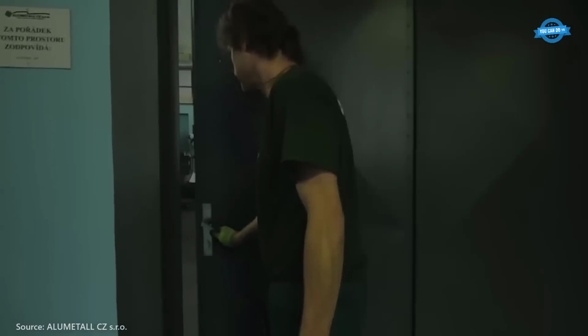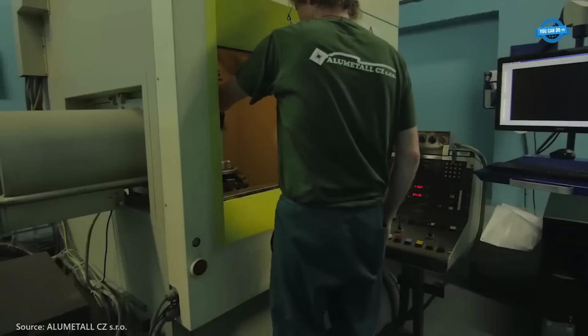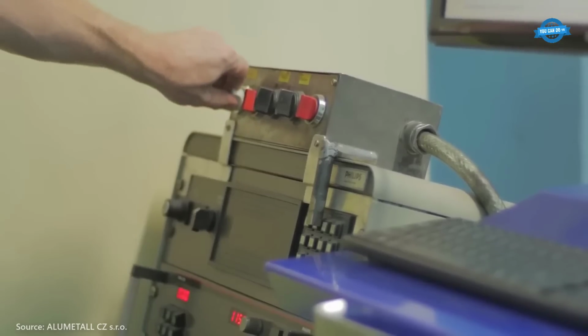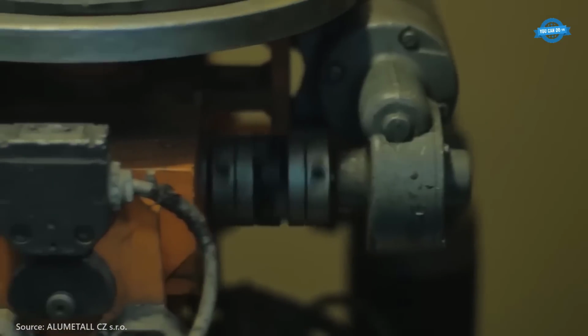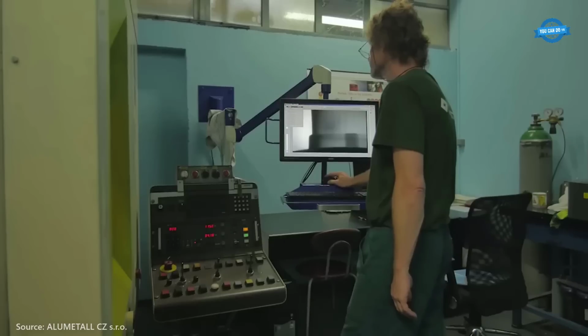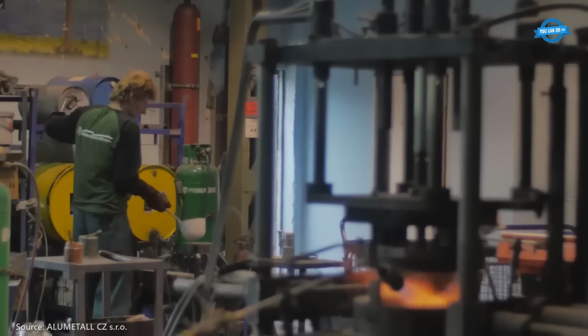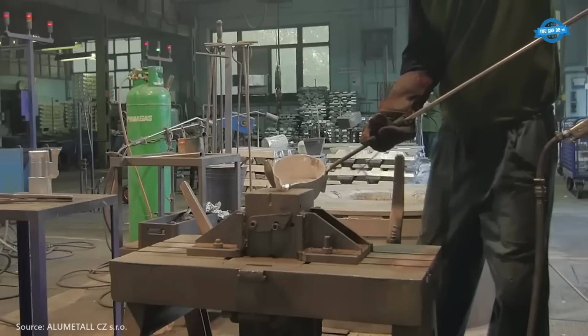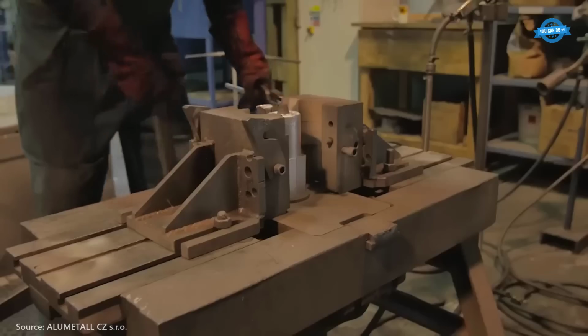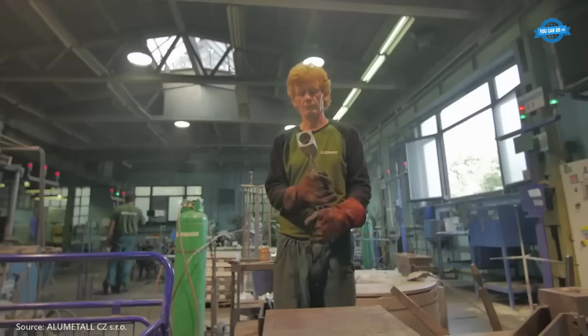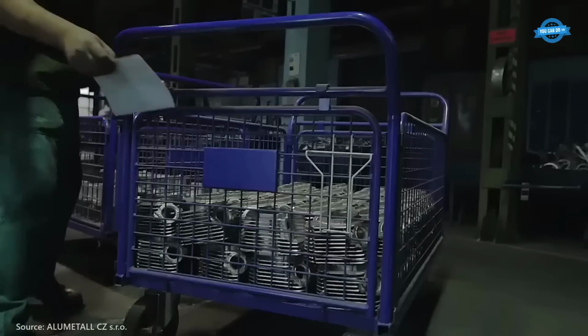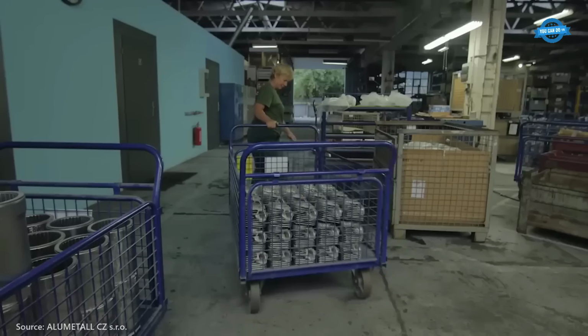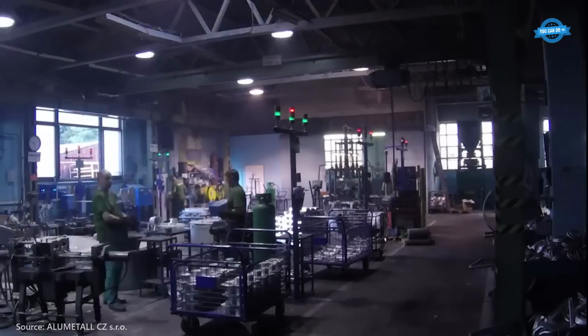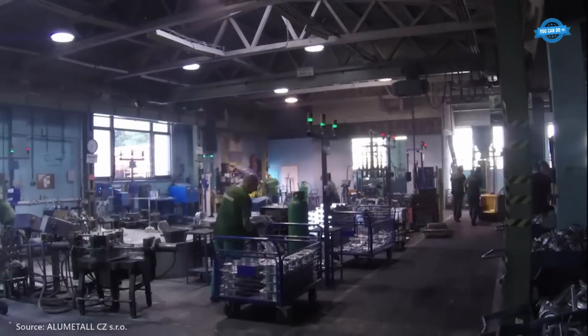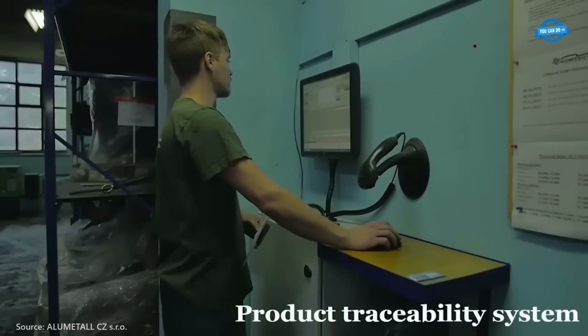After solidification, parts undergo stationary X-ray inspection to detect internal defects such as porosity, cracks, or inclusions. A product traceability system assigns a unique identifier to each casting for quality tracking. To clean the parts, dry ice blasting is used to remove surface residues without damaging the component. The castings then go through quality control processes, including dimensional checks and visual inspection.